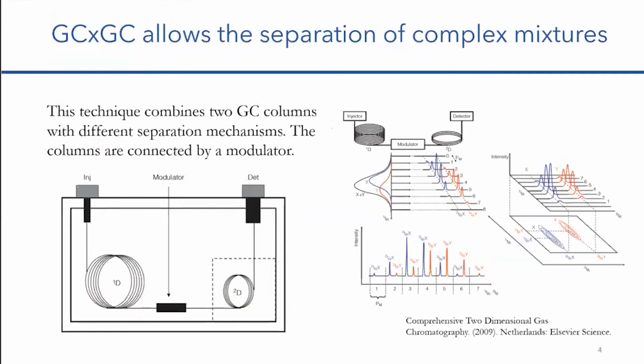Okay, so now I want to talk about GC by GC. GC by GC is a technique that combines two different columns with two different mechanisms, and they are connected by the modulator. So I will explain: the sample goes through the injection port, then flows through the first dimension column. In our lab, we are working with a first dimension column that separates by boiling point. Then the sample goes to the modulator, which is able to send all these samples from the first dimension to